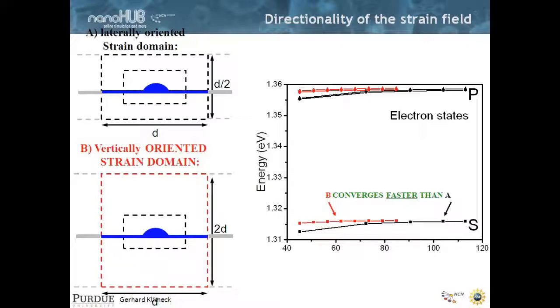And intuitively, you can look at that as well, where you say, well, if you start out with gallium arsenide, and indium arsenide has a larger lattice constant, it needs to contract laterally and it expands vertically, biaxially strained. And if you grow a couple of layers, it's mostly vertical and then it clumps up. So it remains roughly vertically strained, and then in the lateral dimension you really have gallium arsenide dominating.